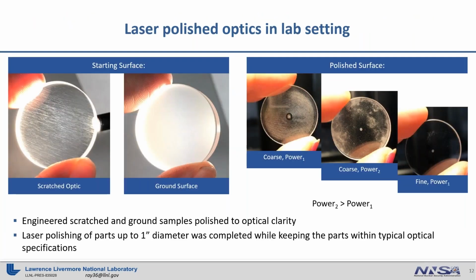So these are a couple of optics that were polished in a lab setting just to demonstrate. And so the starting surface, I'll bring your attention to the ground surface, which is kind of the bigger image in the middle there. And then on the right-hand side, those are 3 optics with 3 different laser polishing recipes. So on the leftmost of that tiered stage of images is a coarse ground surface that was laser polished. And if you look right smack dab in the middle of those optics, you'll see a little circle, because this was all done with annular scanning. So that if you look in the middle, that is how the optic started pre-polishing.